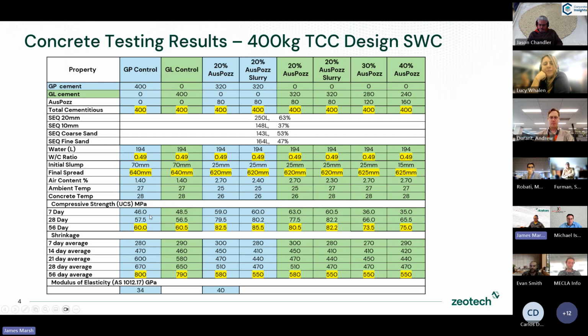So looking at the 56-day strength here, which has been highlighted, about 60 MPa, which is pretty typical for 400 kilos of cement. But then going across with the AusPozz, well, we jumped up to 80, above 80, 85 even, for a 20% replacement. That even stayed very high right across the board, GL and GP. It dropped down a bit at 30% and 40%, but we're still well above both the GL and the GP cement. So even at 40% replacement, we're getting a strong strength gain.